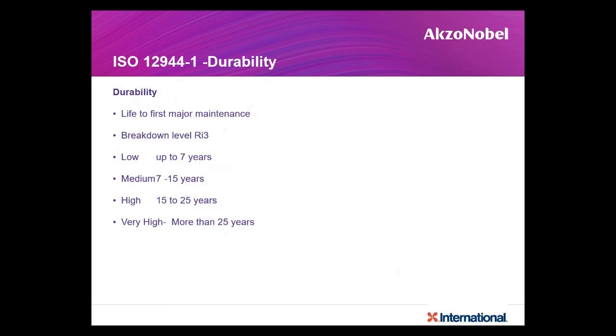We have to find out how much time it takes to arrive at that 1% scattered corrosion, based on which they have categorized it as 4 levels. Low durability is up to 7 years. By the 7th year, you can expect around 1% of scattered corrosion. Medium is between 7 and 15 years. Between this time, again 1% of scattered corrosion. High is up to 25 years and very high is greater than 25 years. So based on this durability expectation, you can recommend coating systems and thicknesses. Keep in mind.